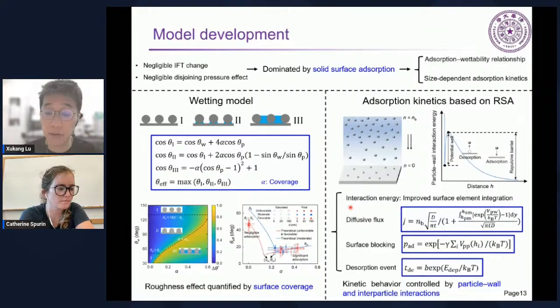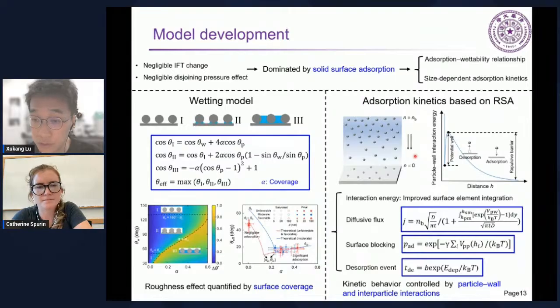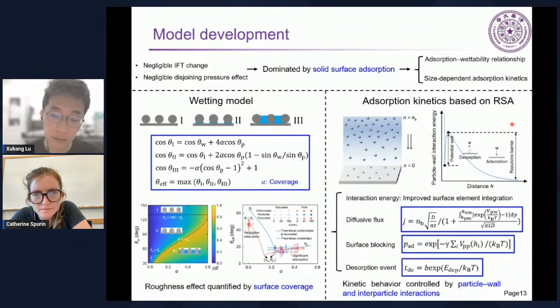So the first step is to improve these descriptions. We try to calculate the interaction energy accurately, and then we derive the critical formulations for the diffusive flux, for the surface blocking effect, and also the characteristic time for the desorption. Here I want to introduce this curve in detail because it is directly relevant to the key mechanism dominating the non-monotonic effect. Here is a typical particle-wall interaction energy curve calculated from the extended DLVO theory.